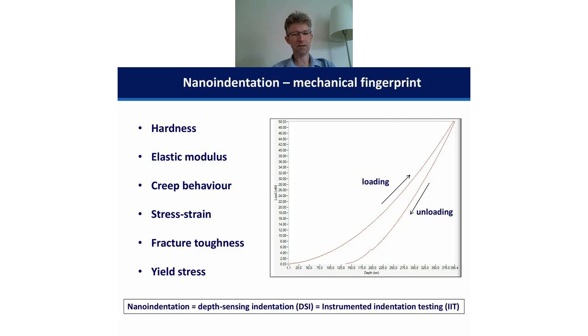Or you can switch to spherical indentation geometries, which allow you to be in a fully elastic regime initially, until as the load increases, at some point there's a move to plasticity in the material, which you may see in the curve as a pop-in, as Andy showed in the example on sapphire. You can relate the mean pressure at which that pop-in occurs to the yield stress through the relationship that the mean pressure at yield equals 1.1 times the yield strength. That's an easy way to do it as well. You can also move to very sharp tips, generate cracks, and measure the length of those cracks to generate fracture toughness measurements. So by subtly changing the type of test we do, we can generate a huge amount of different mechanical property information.